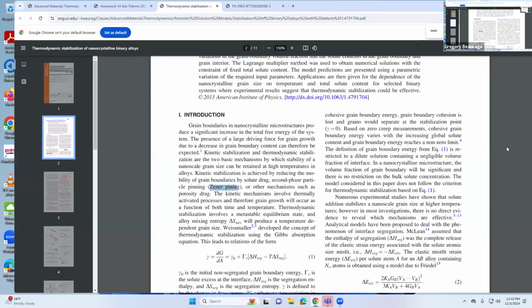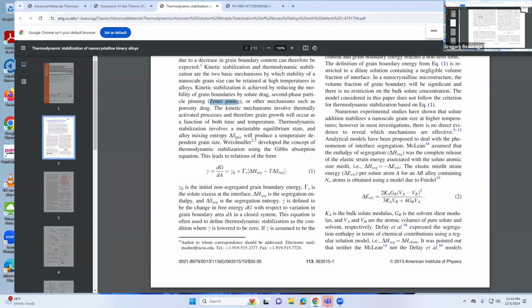At the end, he studies several systems, and he shows it for ones where there's a large mismatch between the atom size of the alloying metal and the matrix metal. Then there's a large strain in the lattice, and that drives the particles to the interface. Then that stabilizes small grains. So you want to have a good mismatch between the sizes if you want to get nano grains, to get large yield stress. Right. So it's kind of a long story, but anyway, there are no simulations in this, even though it seems to be like a simulation paper.